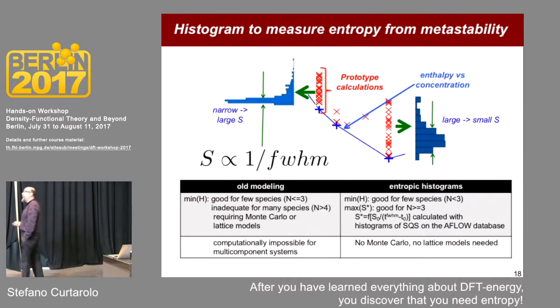So if your database were infinite, which it is not, your T DOS would really be the density of these red dots near the ground states. The blue is the ground states, and the more these dots are packed, the higher is the entropy. So my guess is, well, I don't know what the entropy is, but since I go around the phase space homogeneously, I know where there are more or where there are less. And if I hope to be able to sample the phase space homogeneously in composition and in species, then the density of my red dots needs to be related to the entropy. So I postulate, this is a postulate which is an ansatz, that my entropy can be defined as proportional to the narrowness of the histogram. Okay? And now I have a working plan.